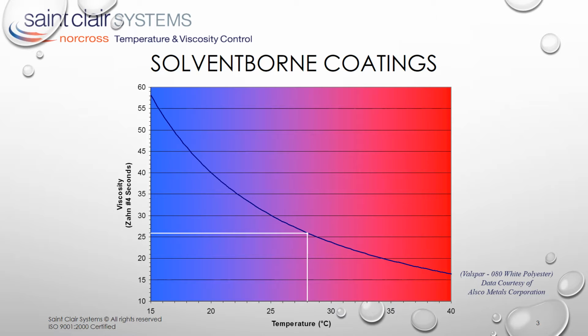As long as it is held at exactly 28 degrees C, it will be at the optimal coating viscosity. But how often does that happen? Oh, right, almost never. And Valspar knows this, so they give us a tolerance of plus or minus 2 seconds to work with. Again, extending this over to the curve and down, we can see that this corresponds to a 3 degrees C temperature range from 26.5 to 29.5 C.